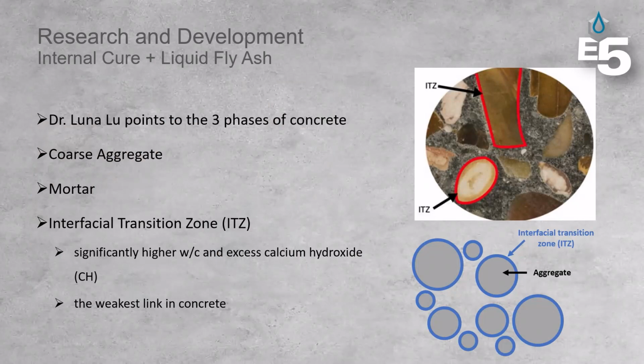In school, we learn about the mortar fraction and the aggregate fraction, and you learn about the interfacial transition zone, but she points to this as a phase of concrete because there's an excess of moisture and calcium hydroxide at that interface around the aggregate. And so what you can see is that that influences the paste to aggregate bond, okay? And so that higher water to cement ratio and calcium hydroxide forms this weakest link in concrete. That's why we see a lot of failures of that paste to aggregate bond.